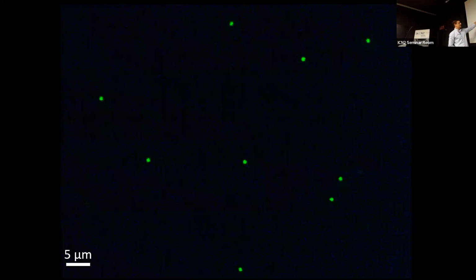This is a dark field image of many gold nanoparticles on a dark background, of course. And these are all individual gold nanoparticles. And then what Rifa did, he flew the ceria growth solution and focused the laser onto this one, then washed everything away with water, and then flew the zinc oxide solution on this one, and then repeated the same for zinc sulfide. And at the end, the sample looked like this.